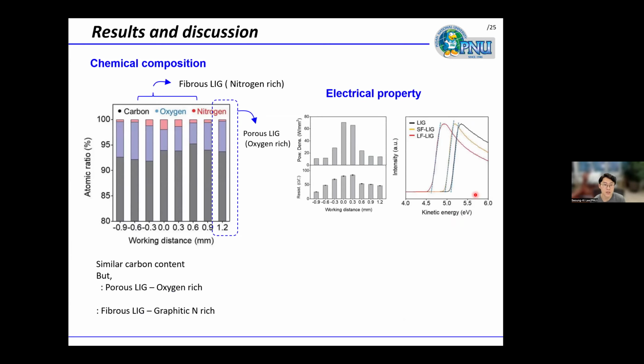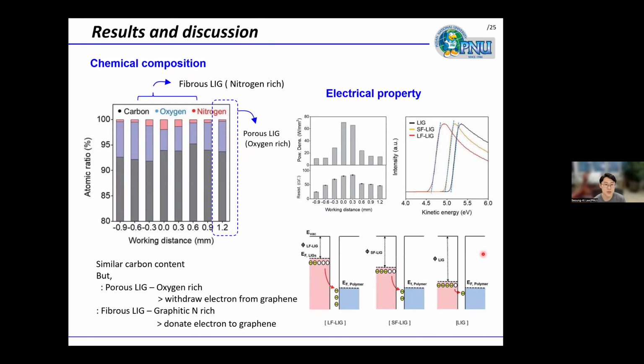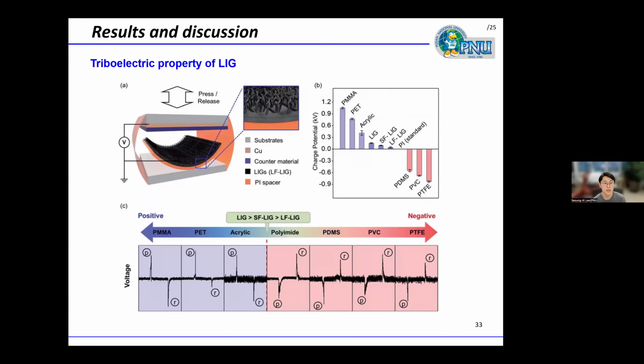This slide shows the result of XPS analysis. As the structure changed, the internal composition of LIG is also modified, which in turn affects its work function. As shown in this UPS result on the right image, the work function gradually decreases as the LIG becomes more fibrous. Based on this characteristic, it means the surface area increases and the work function is reduced.